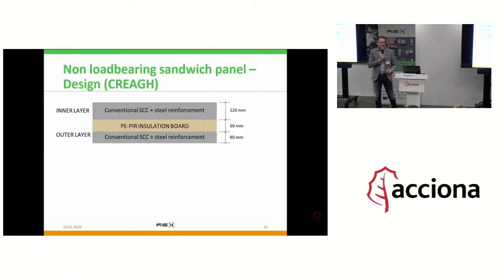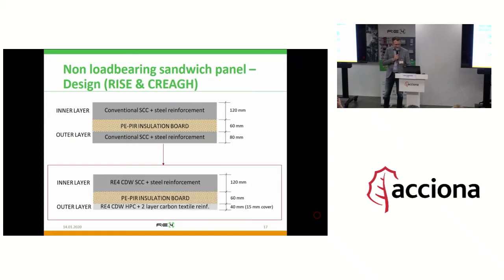So this is a very rough layout of the conventional sandwich panel made by CREAGH, and which was used also for the load-bearing sandwich panel Ruben told you about. The difference from the conventional is that we, exactly like in the load-bearing, use CDW-based self-compacting concrete in the inner layer, but in the outer layer, instead we use a high-performance concrete based on CDW. And we also have a textile reinforcement instead of steel reinforcement.